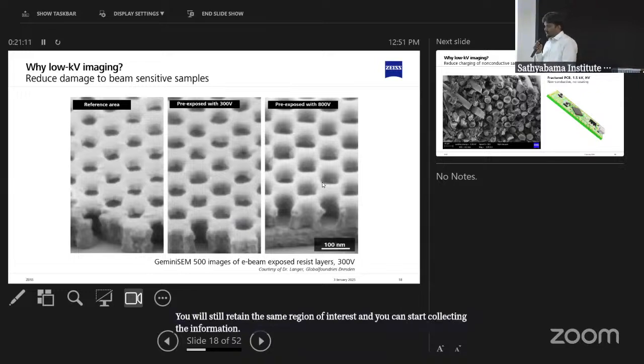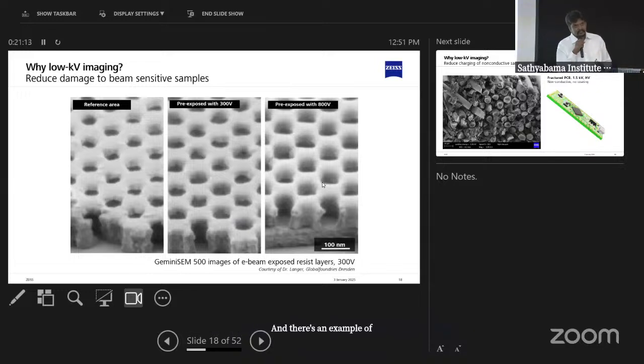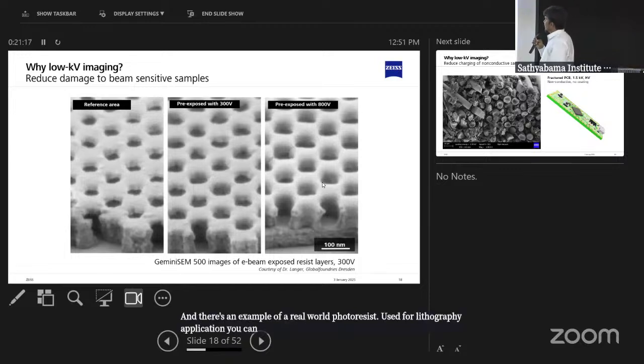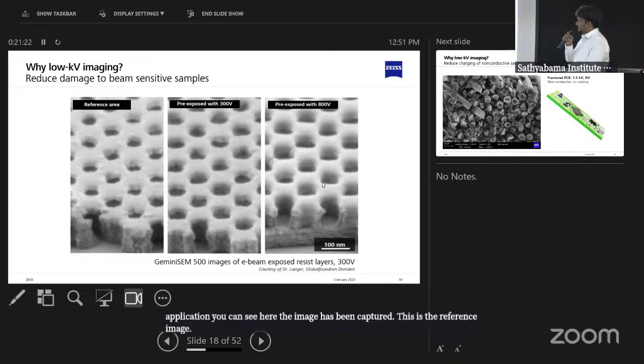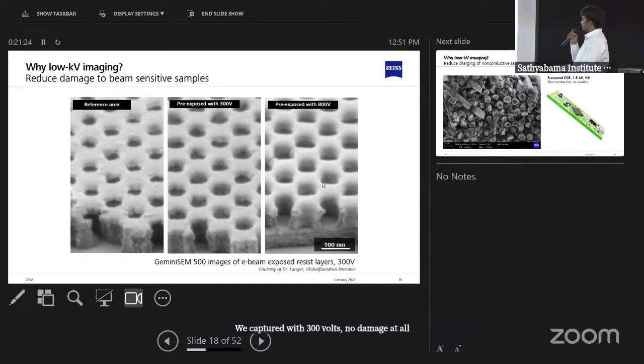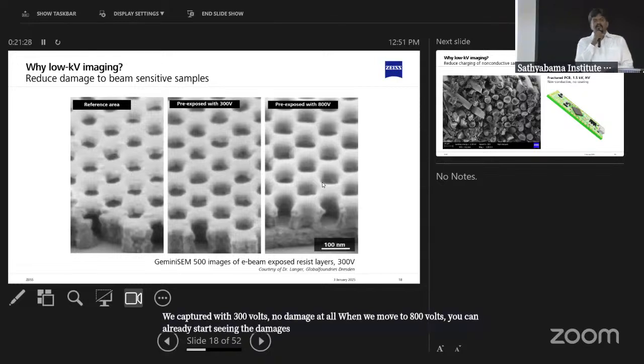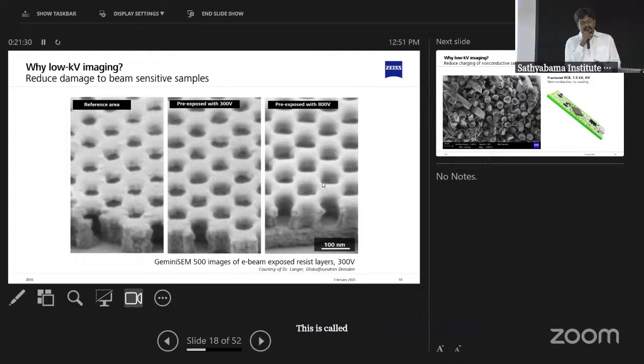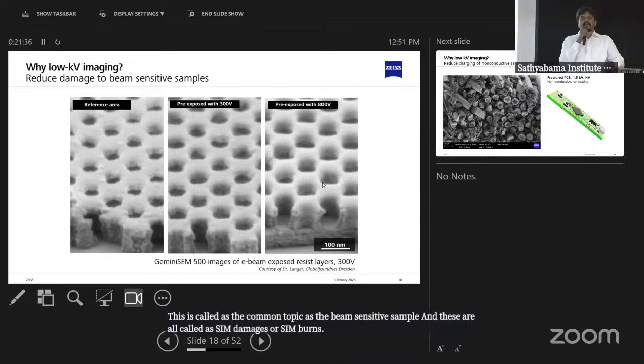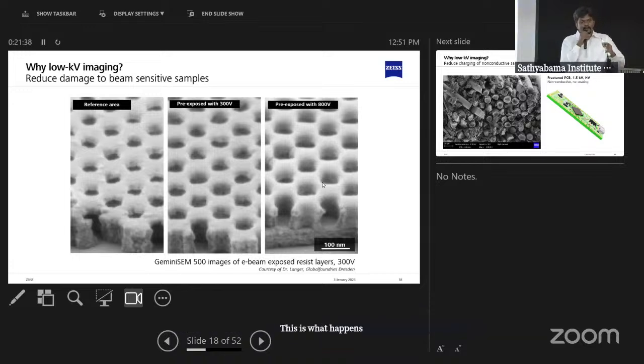And there's an example of a real-world photoresist used for lithography applications. You can see here the image that has been captured. This is the reference image. We captured it with 300 volts, no damage at all. When we move to 800 volts, you can already start seeing the damage has started happening. So this is the common topic called the beam-sensitive sample. And these are all called SEM damages or SEM burns. This is what happens when you don't use optimized operating conditions for collecting the information.